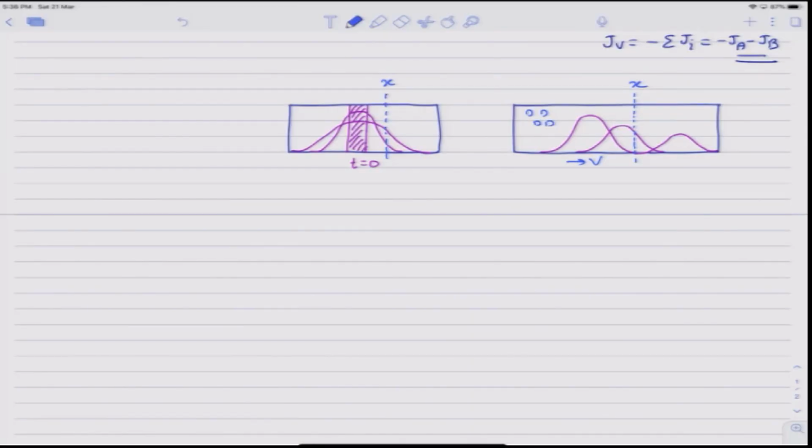And that can be done if we place these markers on the initial contact plane before we sandwich the two alloy blocks before the start of the diffusion experiments. Typically, the oxide particles like alumina or yttria are used for this purpose.